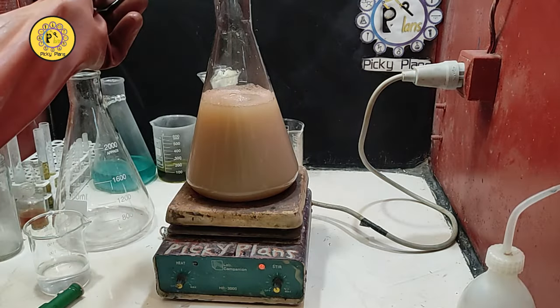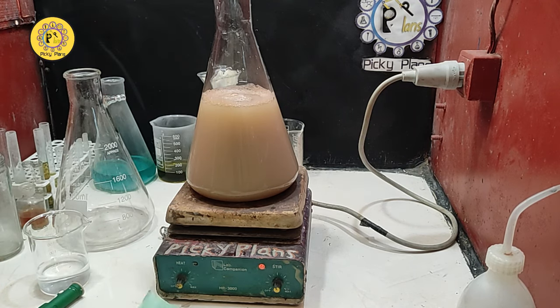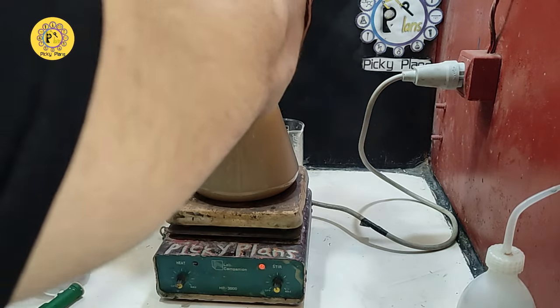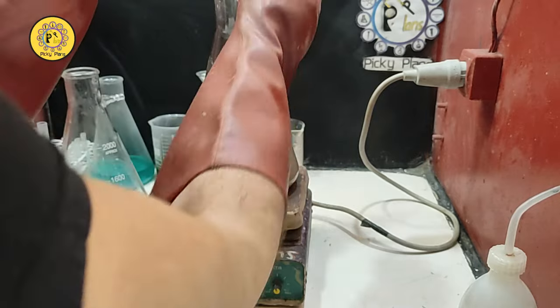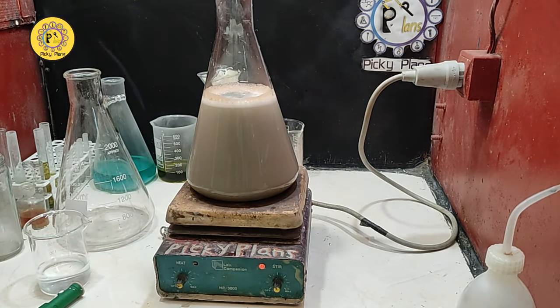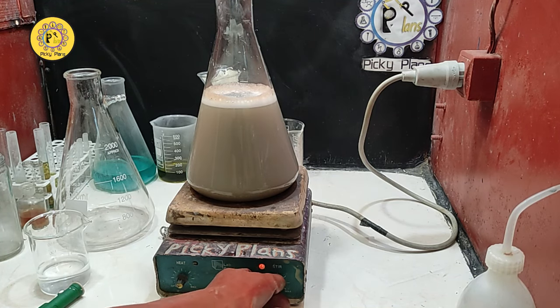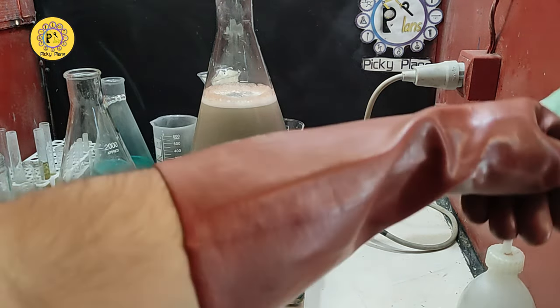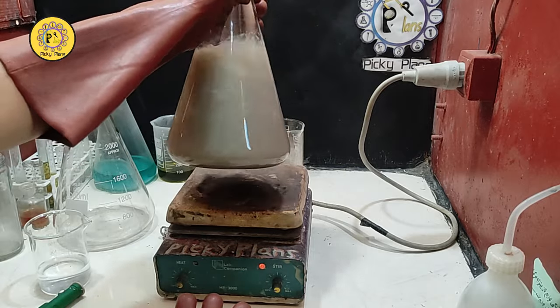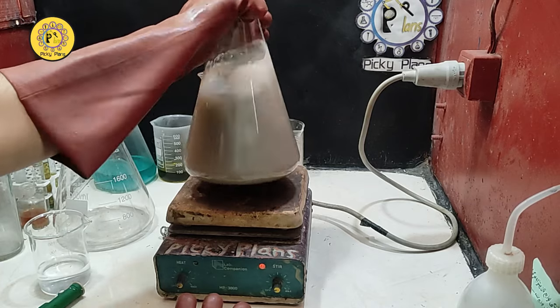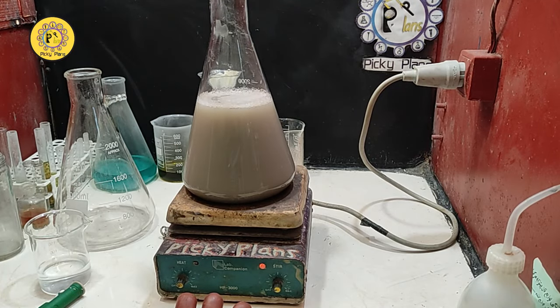Here is 5 grams of zinc metal to be added to the solution to start cementation. Agitating will help a lot to accelerate this process. Retention time in acidic pH totally depends on the reaction which the zinc powder goes through, and when we get the solution pH of around 6 to 7, the cementation in acidic pH is done and we have to alkalize